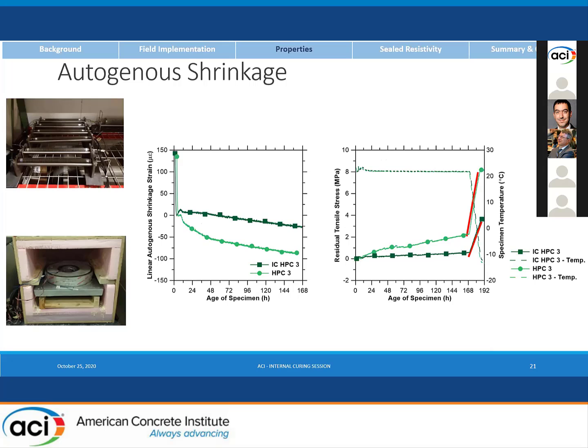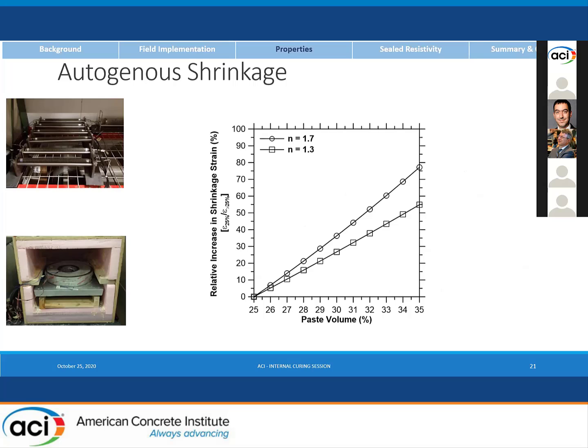You can see that we have different rates of stress generation when we drop the temperature at that point. And then you can see that the total magnitude of the stress is reduced here. So the primary thing that's going on there is actually that internal curing will reduce the coefficient of thermal expansion at very early ages. The secondary contribution is that there is a slightly lower stiffness, so there's more relaxation in the system. And then I'll leave it at a note that all of this does scale with paste volume. And so here's just a reference for you in terms of what that relative magnitude would be related to 25% paste content.